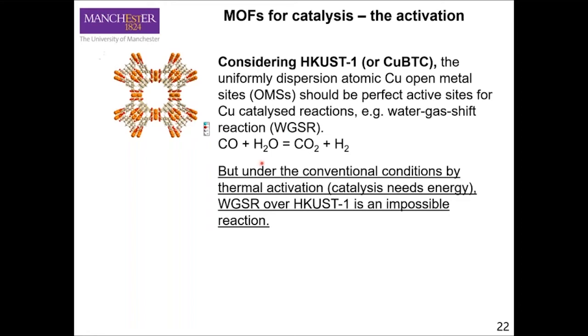But the thing is, this MOF does not like water because water can damage it. And for water gas shift, at least we need 200 or 300 degrees Celsius to activate the reaction. So in theory, this is a very good catalyst for water gas shift, but in practice it is not going to happen, because water is going to sit over here before the copper works as a catalyst. Basically, at high temperatures, the water will damage it. So under conventional thermal conditions, this dream catalyst is not going to work for the reaction.